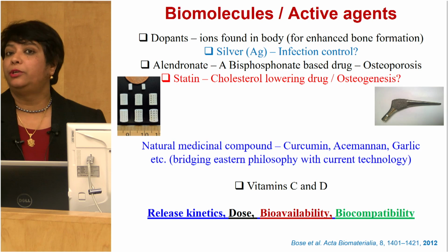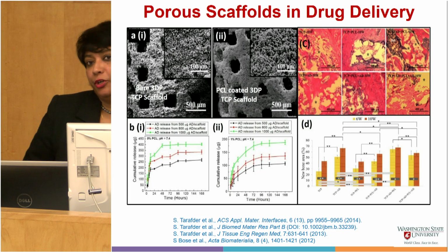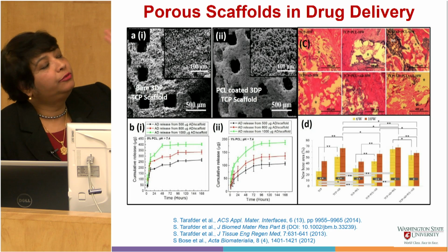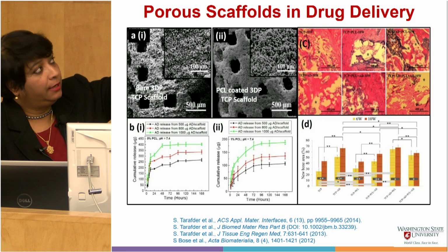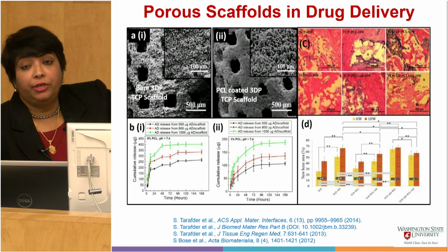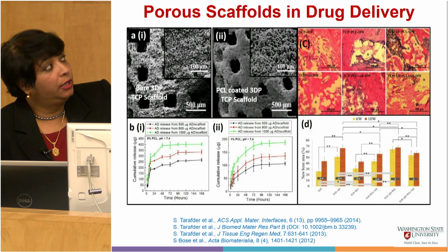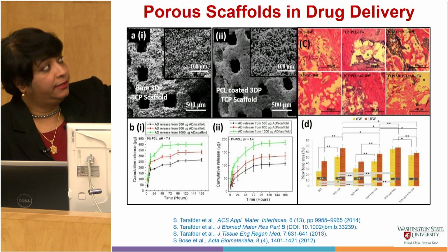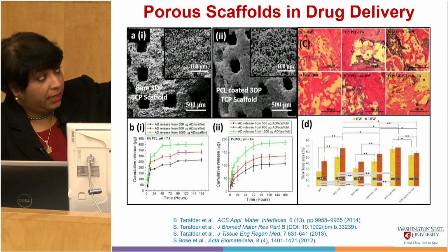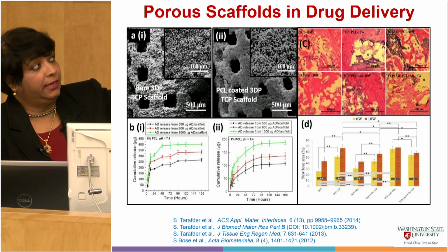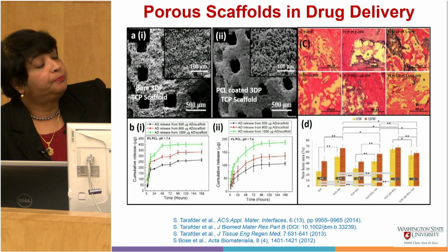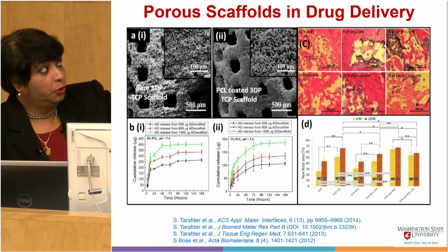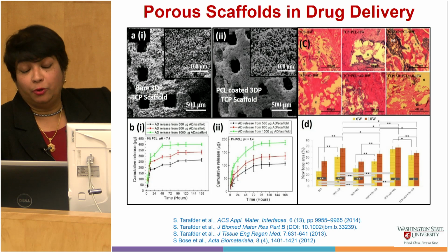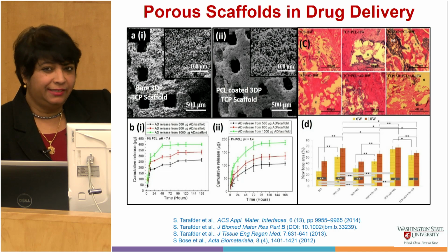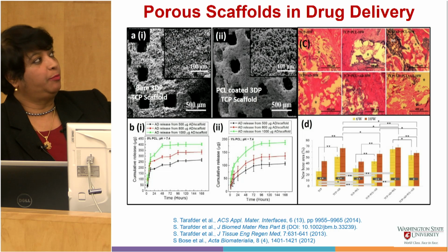I know it is a crowded slide, so the point that I'm trying to make here is we use the porous scaffold on the top left, you are seeing. We used polymer to control the release kinetics. Some of them you can see the steep release kinetics, some of them you can see a little slow on the right hand side plot. So we control release kinetics using polymer. This is also a concern with ceramic material.